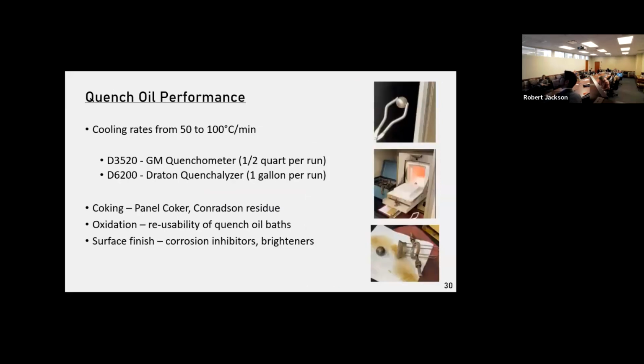Okay, so quench oil. The way you can measure quench oil performance, there's two main tests. There's the GM quenchometer test. This is a really cool test where you heat a nickel ball up to about 850 degrees Celsius and then drop it into your quench oil. The interesting thing about nickel is when it gets to about, I think about 600 degrees, it becomes magnetic again. So you go above the Curie point, the nickel ball cannot be magnetized or has no magnetic attraction.